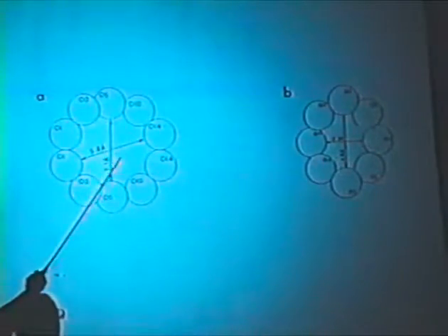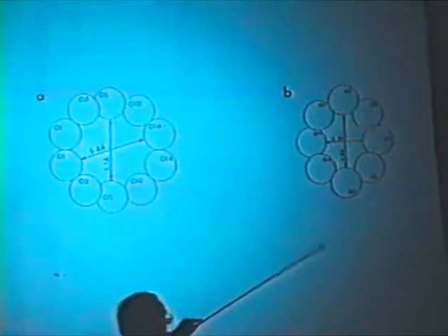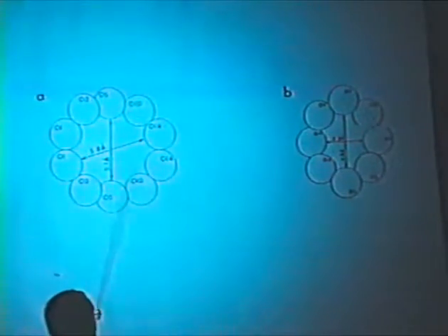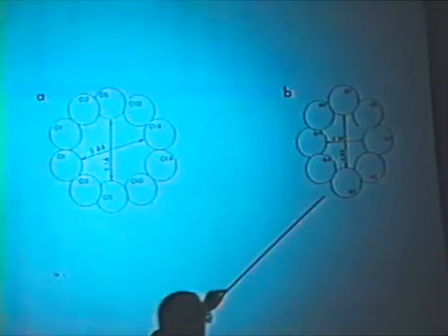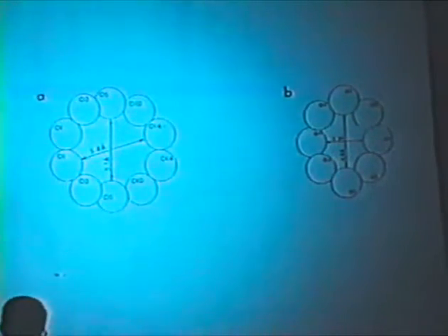The 10 ring has dimensions about 5.1 by 5.8. This is slightly larger than the 10 ring in ZSM-5 and considerably larger than the 10 ring in ferrierite. The other ring, the 8 ring, which runs perpendicular to this, is an intersecting 8 and 10 ring system. This 8 ring has almost exactly the same dimensions as does ferrierite or ZSM-35.